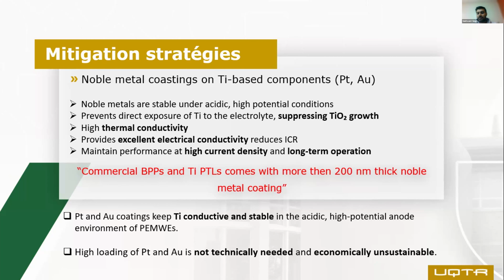You can make a guess how costly these are actually. Commercially available bipolar plates and titanium PTLs actually come with more than 200 nanometer thick noble metal coating. That is the main bottleneck of PEM water electrolyzer technology, apart from the catalyst and the membrane part.